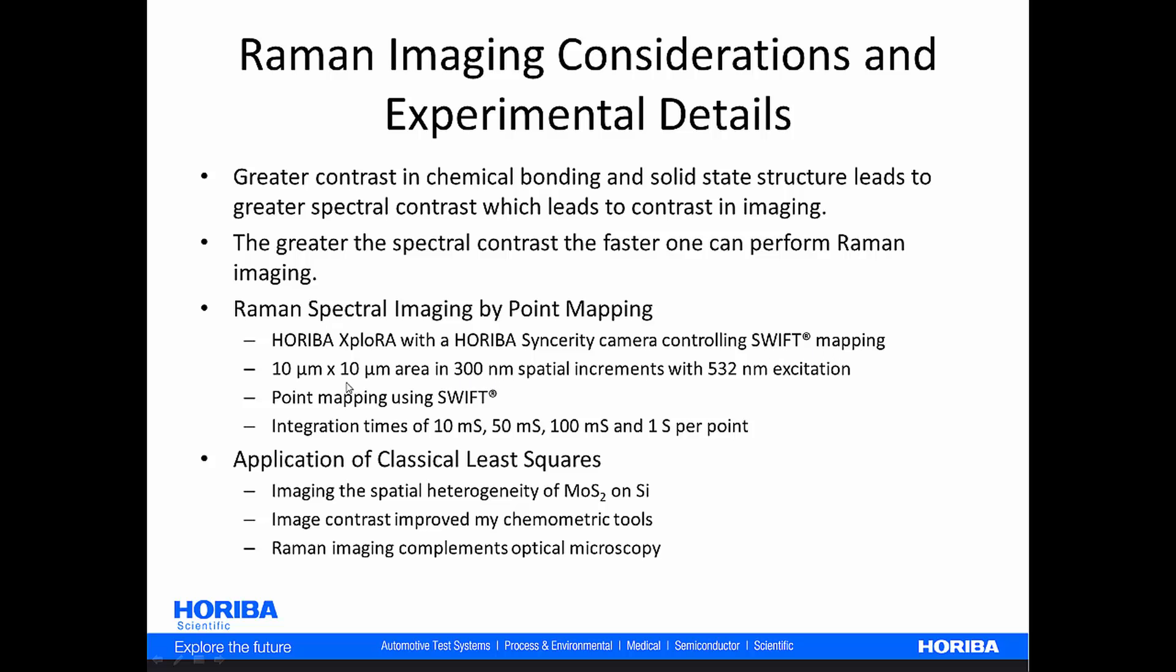The areas that we mapped are 10 by 10 micrometer areas in 300 nanometer spatial increments with 532 nanometer excitation. And as I said, we're using SWIFT. And here are our integration times.